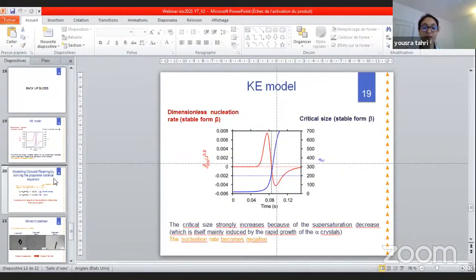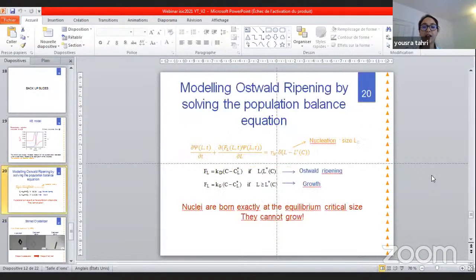We have seen that in our population balance model, the clusters will grow if they have a size higher than the critical size, and they will dissolve if they have a size lower than the critical size. We came to the point that the nuclei are born exactly at the equilibrium critical size, and actually they cannot grow. So this model cannot take into consideration the ripening mechanism that comes from the size-dependent solubility.